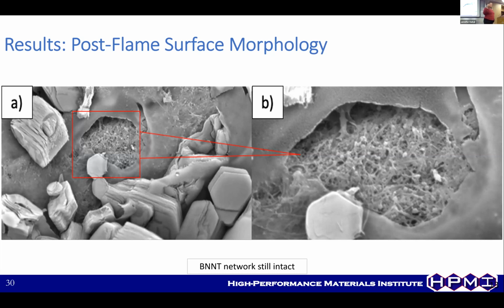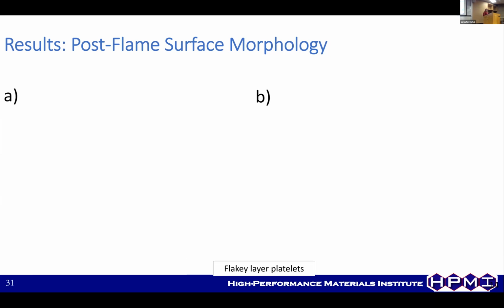I actually got a call from my students at the SEM saying, I have no idea what we just found. We have no idea what we're looking at. And so we have some really unique crystalline structure, but underneath this melted thermoplastic layer, you can still see intact BNNTs. So at least from that 105 second exposure, we don't have full loss of that protective layer, which is potentially a good thing if you're doing reentry into atmosphere kind of studies.